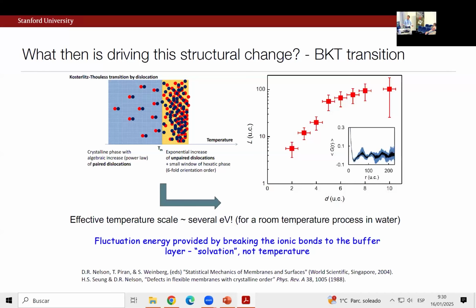In any case, why or how could you map some of these ideas to the system of this freestanding membrane? This is a cartoon image from Seung on how you might think about this kind of transition. Formally, a long-range order exists in the T=0 limit, but at finite temperatures, this system is stabilized by bound pairs of, say, vortex, anti-vortex defect pairs. As you go up in temperature, the number of these grows in some power law. And the so-called BKT transition is when these things unbind and exponentially proliferate.